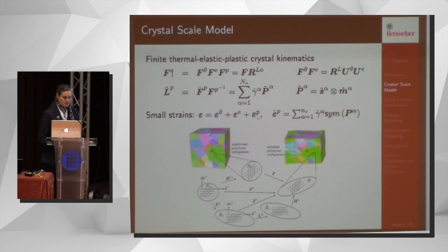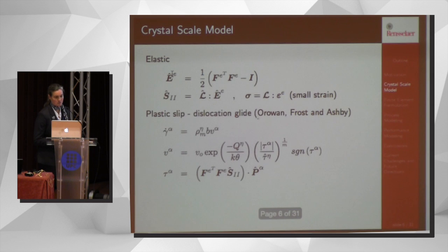For small strains, if we're doing a small strain analysis, we do an additive decomposition of the small strain tensor, but our plastic strain rate has a similar form to the plastic velocity gradient, where now we're looking at the symmetric part. And the anti-symmetric part, of course, is associated with the lattice rotation due to plastic straining.